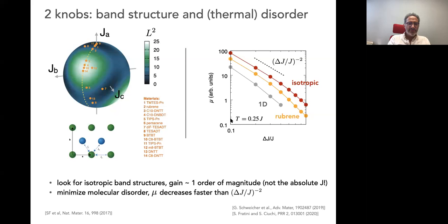So the take-home message is that you should try to look for isotropic band structures, minimize molecular disorder, and you have a lot of margin for improvement. And as Henning was correctly saying, it's not really the absolute value of the transfer integrals that matter, because you might have very large transfer integrals in one direction, but then the thing is one-dimensional and it's very, very sensitive to disorder, and you'll get localization and very low mobilities.